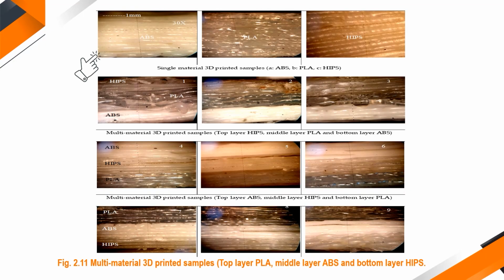Like you can see in this first case, at 30x magnification, the ABS was printed and we can clearly see the layer by layer printing of material. Similarly, that layer by layer fabrication in case of PLA, layer by layer fabrication in case of HIPS was also observed. Now, once we do this with a multi-material, like you can see case 1, I have ABS printed first, followed by PLA. You can see some globule formation is observed. That means once I print the material like this, in which the PLA will be in the center and HIPS will be in the top, there will be some side flow of the material. Whereas if I put PLA first, HIPS later, there is no side flow.